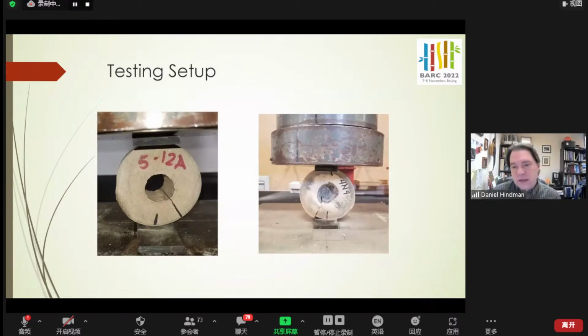This is the testing of samples. On the left, we have an internode ring, and you can see how this has started to fail after compression. We used a set of strips of rubber on top and bottom of the sample just to apply pressure so that force was not applied at one point. And the picture on the right, you can see is a node, and you can see about a 15-degree fracture going from the upper right to the lower left in that piece.